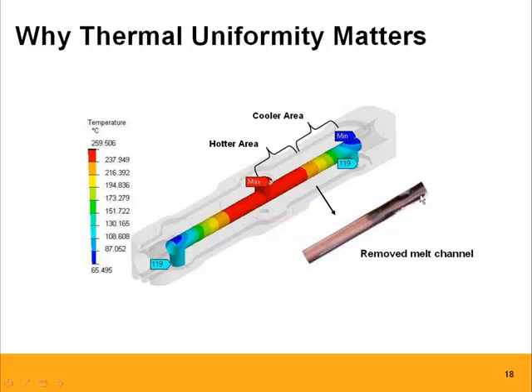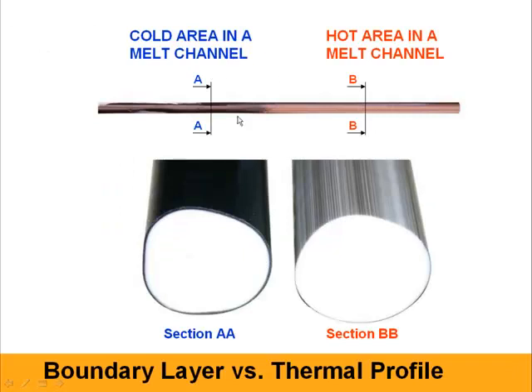So this is the blown up version of this. In the cold area in the melt channel, section AA, you can see clearly a lot more boundary layer. This is the same injection condition, the same hot runner, just two different sections in that hot runner base at two different temperatures. And then on the other hand, you see the BB section view, with significantly reduced outside layer. Now you can imagine the effect on color change: it will take a lot longer to clean out section AA versus cleaning out section BB.